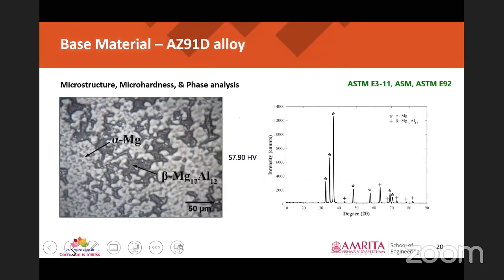Coming towards the microstructure observed under a normal microscope, we could see alpha phase and beta phase in the alloy. Alpha phase is observed as a bright region, and beta phase is observed as a dark region in the optical microscope after etching. We have done some XRD analysis to confirm the phases present in the matrix. The XRD result confirmed that there are only two predominant phases present in the AZ91 alloy. One is alpha magnesium, which is the primary phase, and the second is the intermetallic phase between magnesium and aluminum, that is beta Mg17Al12. So these are the two phases present in the AZ91D alloy, and the microhardness of this alloy in the as-fabricated state is around 57.9 HV, that is, Vickers hardness of 57.9 HV.